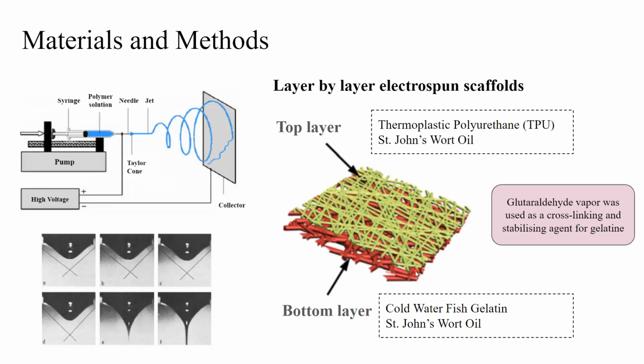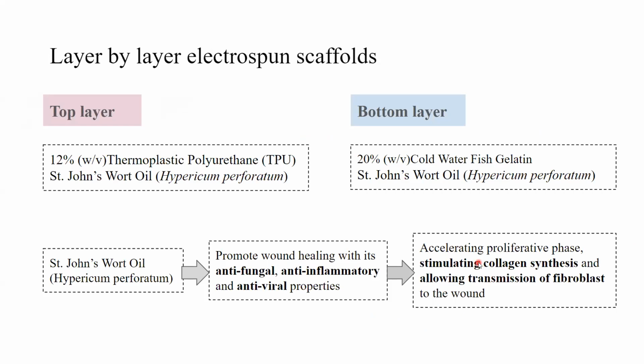Additionally, glutaraldehyde vapor was used as a cross-linking and stabilizing agent for gelatin. Just to make it more specific, the top layer includes 12% of thermoplastic polyurethane, which is TPU, and the bottom layer includes 20% of cold water fish gelatin. Oil was added in amounts equal to 30% of polymer's weight into both polymer solutions.